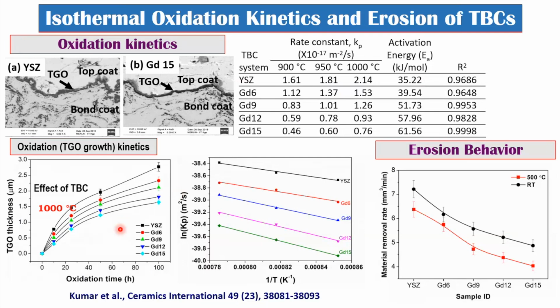And as a result, the growth of the thermally grown oxide is reduced significantly. For example, this is the TGO thickness as a function of oxidation time, and you see the bottommost layer is with 15 mole percent of Gd2O3 added. This shows the slowest kinetics of oxidation, meaning the oxidation resistance is the largest. So these are various kinetic data analyses to prove that it's indeed very effective, and it also shows higher erosion resistance, shown here by this red curve.